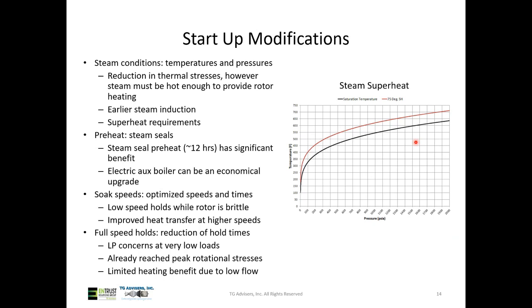And some startup processes, there's quite a bit of variation across the industry, but some OEMs actually call for you to slow down the process at that point. And typically we're not a big proponent of that because there are some challenges of sitting at low loads for very long periods of time. We have to worry about LP blade vibration. We have to look at back pressure levels very closely. And we don't get a ton of additional heating because you're not getting a lot of flow at that low load point. So when you look at temperature trends, you tend to kind of level out over time. So I think you have to look at all these things and you can make some good judgments on where there's opportunity to make modifications.